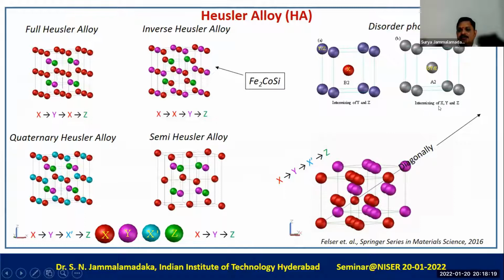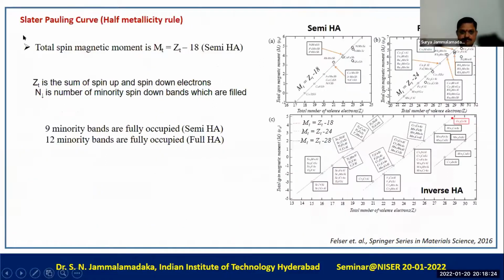And if the intermixing happens between X, Y, and Z, that is called A2 phase. So these Heusler alloys are found to follow the Slater-Pauling curve, which is basically the half-metallicity rule. The Slater-Pauling curve is essentially between the total number of valence electrons versus the total spin magnetic moment, MT, which is defined as ZT minus 18 in the case of semi-Heusler alloy materials. Over here, ZT is the sum of the spin up and spin down electrons.